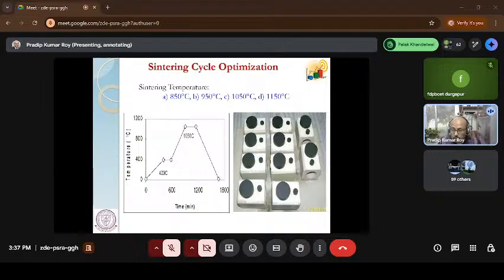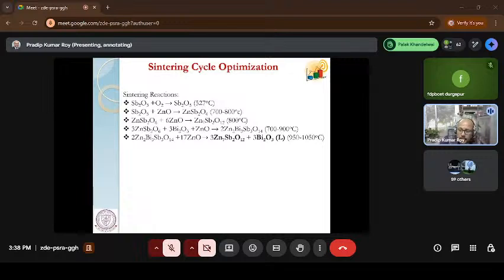So we have optimized the material, and as I said, it's a nano material, so we have to optimize the sintering temperature also. Normally, the material is sintered around 1200 degrees Celsius, and if it is nano, the sintering temperature should be less, because it actually helps us to increase the sintering aspect. So we did it at 4 different temperatures: 850, 950, 1050, and 1150 degrees Celsius. Then these are the different reactions that happened during the sintering method.